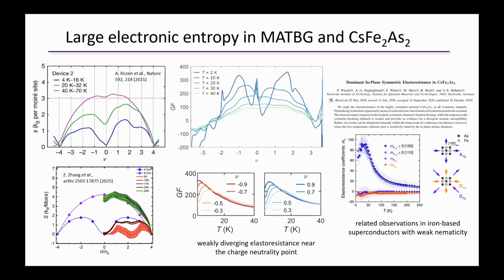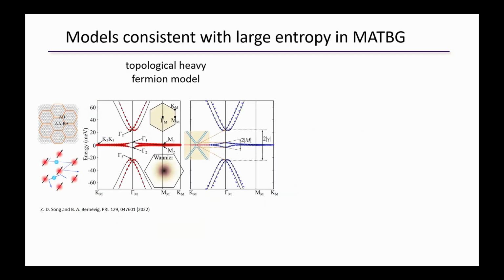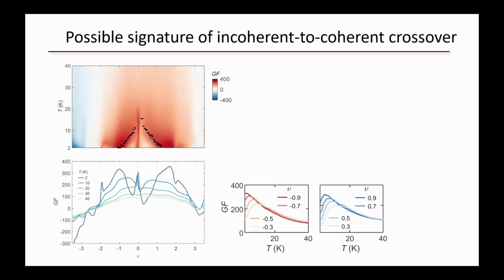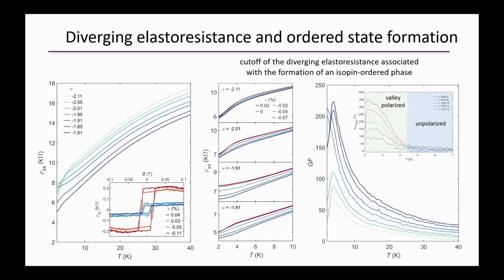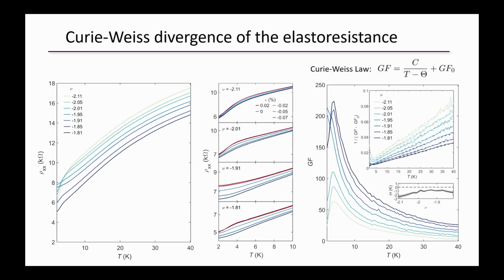Right, in the cesium one, it's almost entirely from the isotropic channel. In like barium doped pnictides, then it's almost entirely from the anisotropic channel. So I think when it's from the isotropic channel, then the considerations you mentioned about strain coupling to effective mass are the right direction to go in.